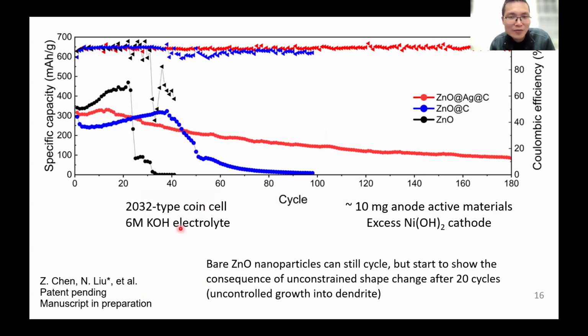And we tested the battery performance. So the red one is the structure that you just saw, and the blue one is the zinc oxide carbon core shell structure. There is no silver, so they are better than the zinc oxide particle. They last longer, but still they decay around the 50 cycles. And the one with the silver lasts longer than both the black one and the blue. So this shows the success of this kind of design.